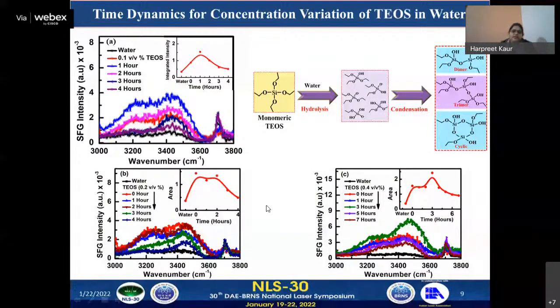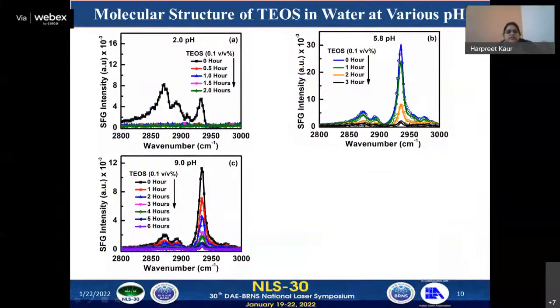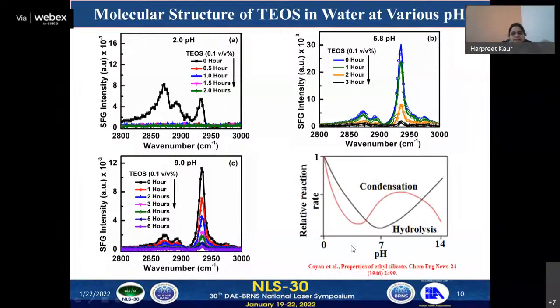Further, we have studied the pH effect on the interfacial structure dynamics of TEOS at the air-aqueous interface, in which we have found that the elimination of the CH moiety is much faster at lower pH values as compared to that at higher pH values, which confirms that the rate of hydrolysis is much faster at lower pH values. This is also supported by the literature, from which we can see that at lower pH values, the rate of hydrolysis is faster as compared to higher pH values.